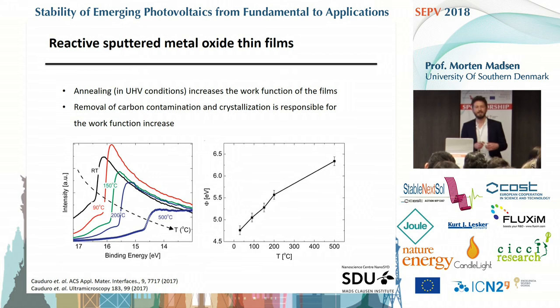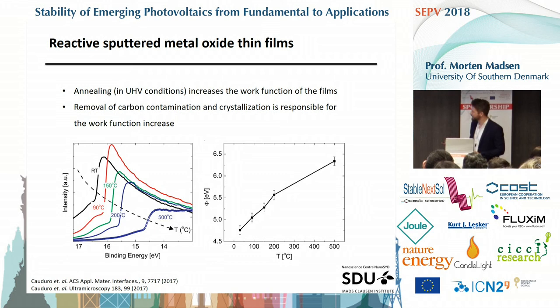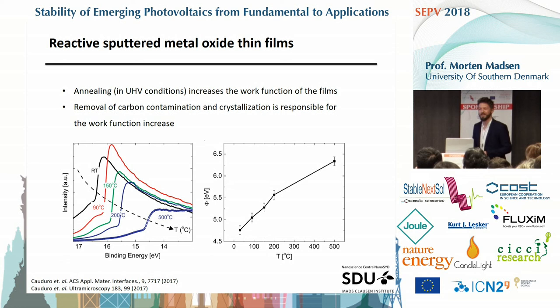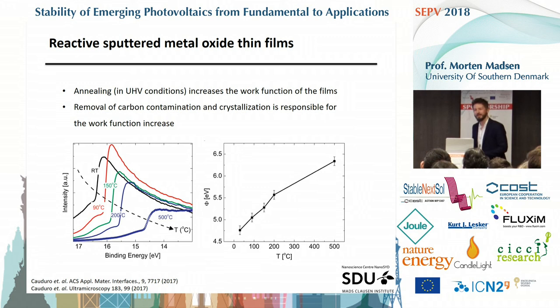These are samples grown in our lab and then shipped to France where the UPS is done, so they have seen air, which may also influence what you measure. Part of the work function increase that happens when you heat up the sample is also that you clean the sample in situ while probing the work function. But definitely what we see is a large peak happening when you heat up further after deposition that comes from a structural reorganization or crystallization of the metal oxide. Even around below 200 degrees, we have no more carbon contamination on the surface but still see a big increase in work function—so you can increase the work function by annealing, which should have good application properties for devices.